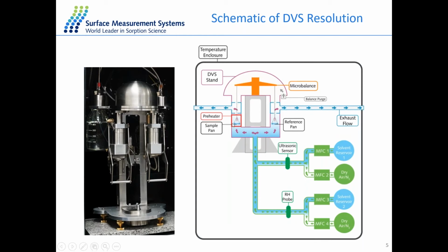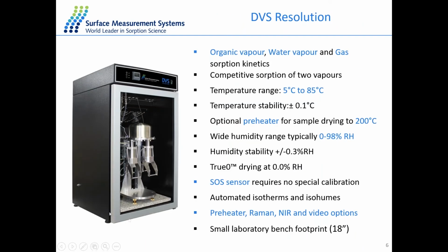And the sample inside this chamber here will pick up the moisture, and the mass change will be recorded by the balance. And the whole stand, like this one, will be set in an incubator with the temperature range from 5 to 85 degrees. That means we can perform the experiment with the whole range of temperature from 5 to 85. And in case you want to precondition the sample at higher temperature to remove the moisture beforehand, we also have an in situ preheater that allows you to put the preheater inside the system, and you can precondition the sample up to 200 degrees before the experiment.